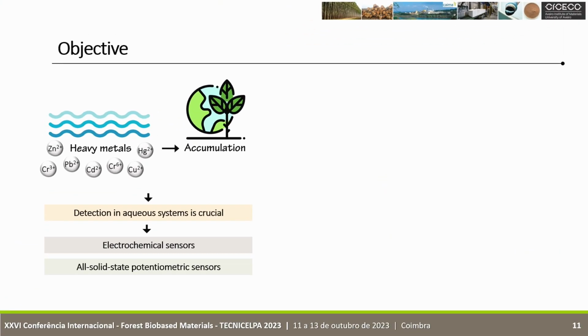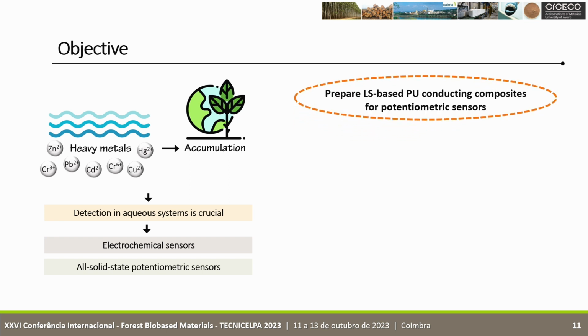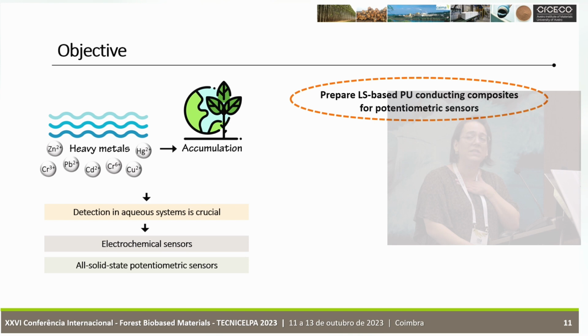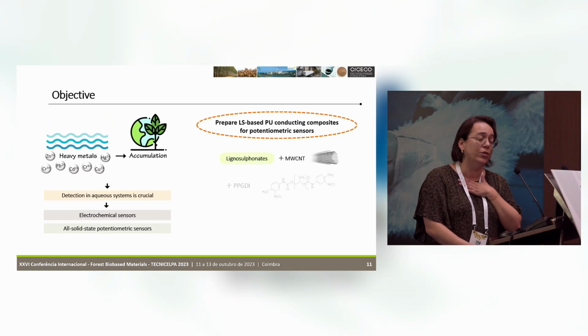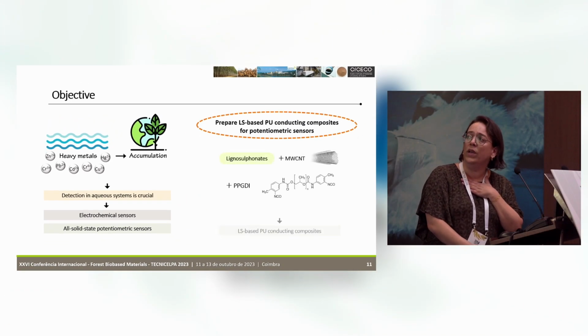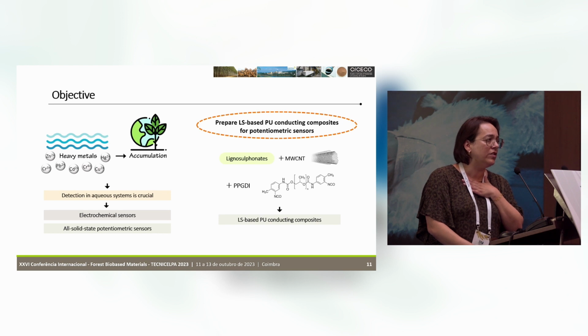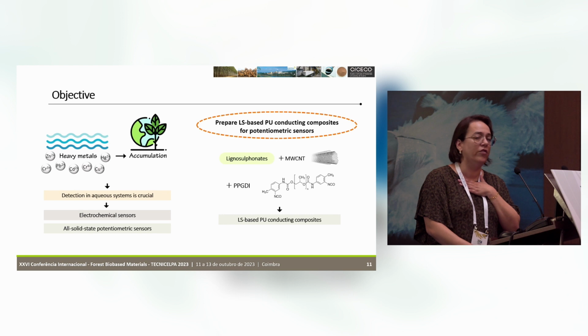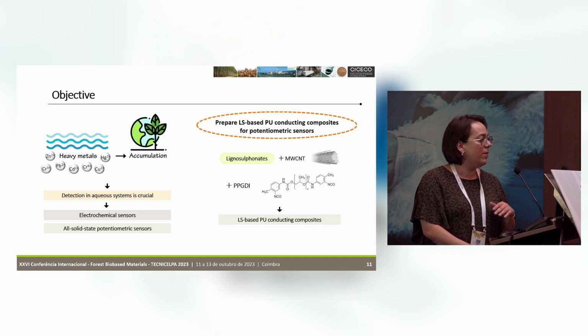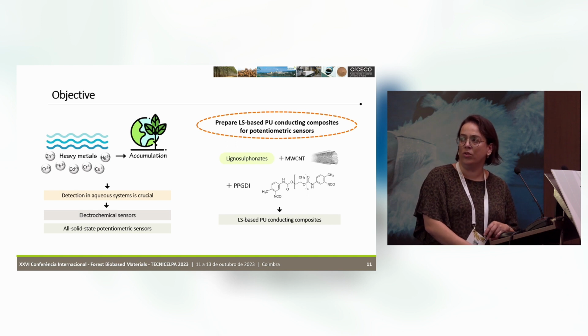In this case, the goal was to produce a lignosulfonate-based polyurethane conductive composite, where lignosulfonates were used as the polyol, mixed with carbon nanofillers such as multi-wall carbon nanotubes to increase the electrical conductivity of the composite, and the isocyanate, which is kind of unusual, but has a flexible chain to impart some flexibility to the final product.